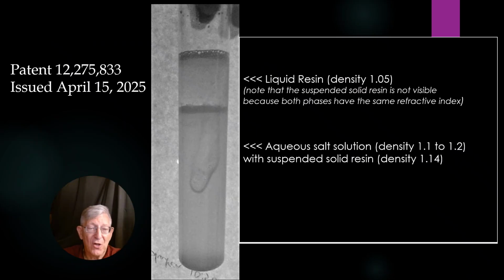Now, as I was talking, we encountered two problems in working with this. One is that if you just take a liquid resin and you shoot a proton beam in it, you're likely not to be able to tell if anything happened, because it turns out that the solid resins have refractive indices that are very close to the refractive index of the liquid resin. And so they just sort of disappear in there. It's like you can't see it. And so we have this problem of visibility, that, like, have we done anything or not?